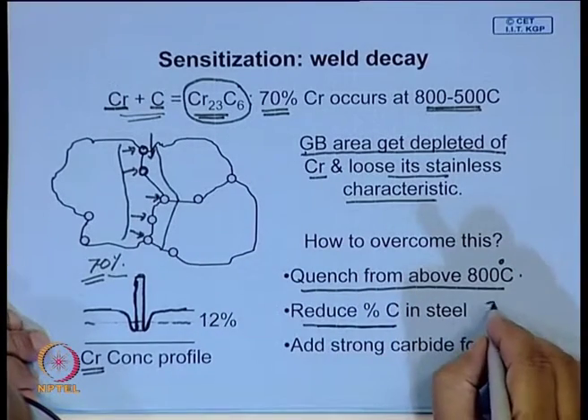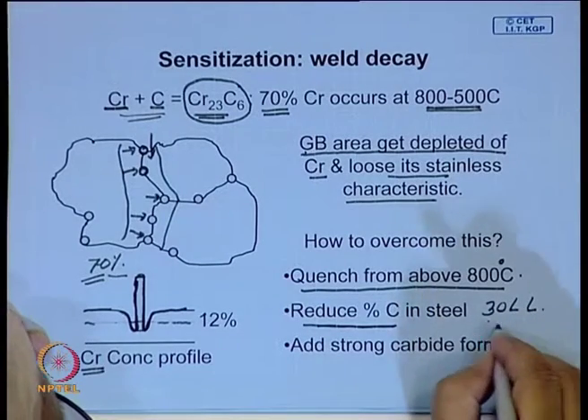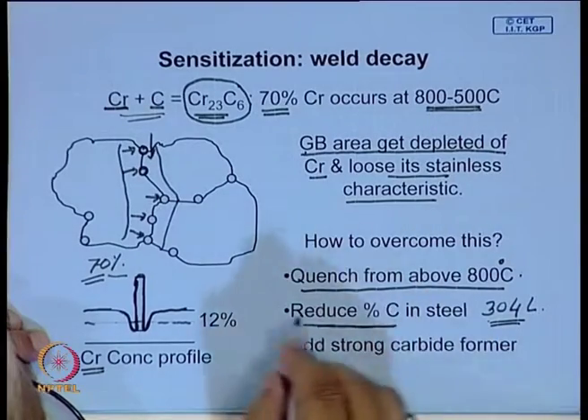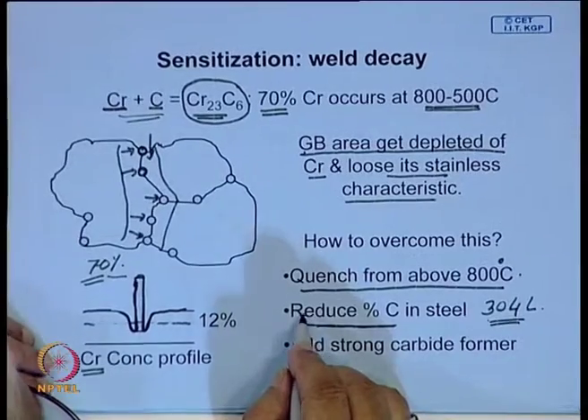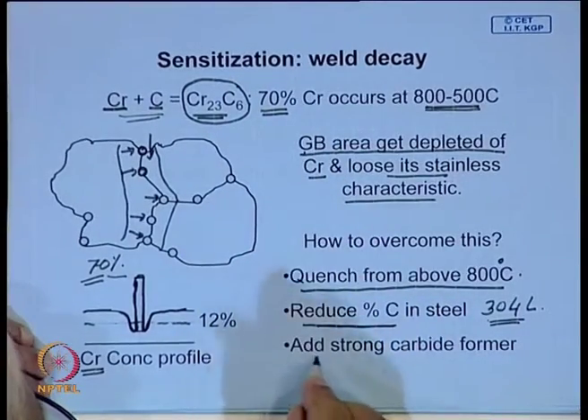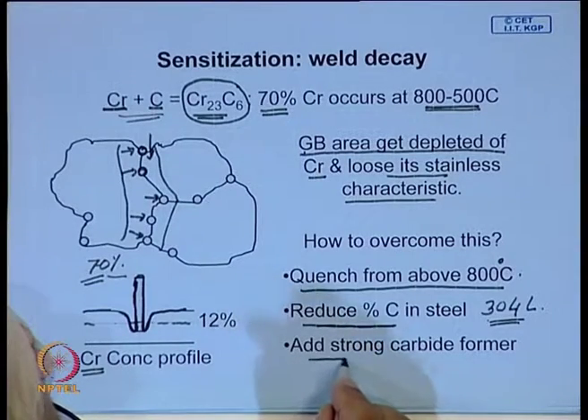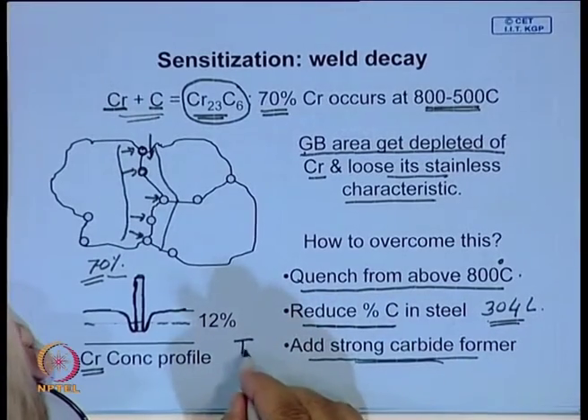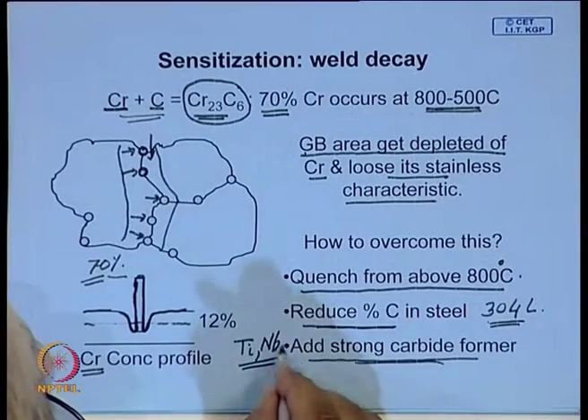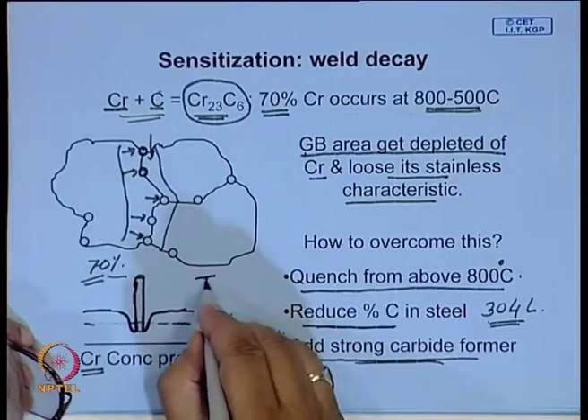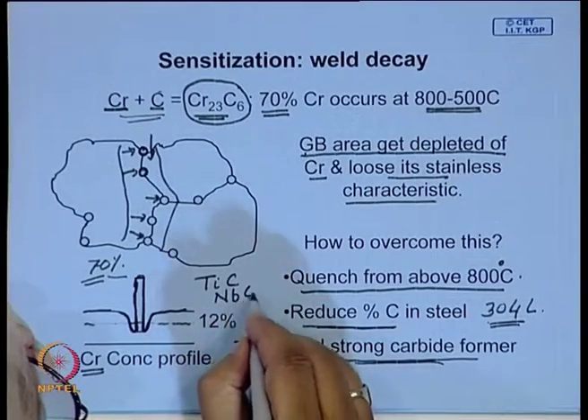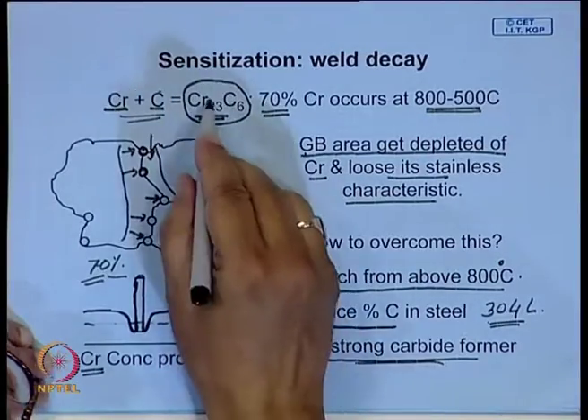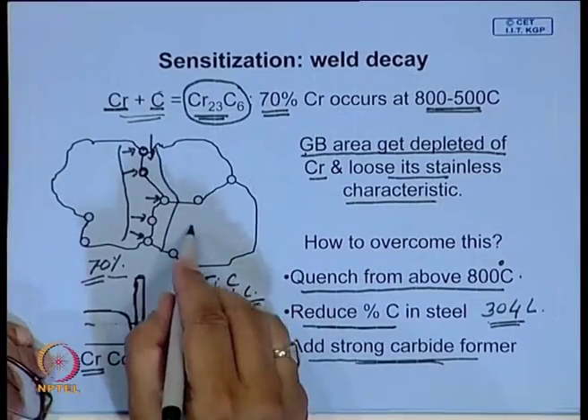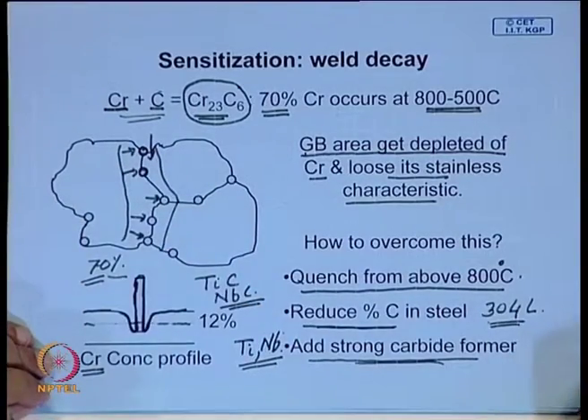So, there are certain grades like 304L with a very low carbon. In that case, it will not be susceptible to this sensitization problem. Another, more common way of avoiding it is to add a strong carbide former like titanium or niobium. This reacts with carbon and forms titanium carbide or niobium carbide, which have a stronger affinity for carbon than chromium. Therefore, chromium does not get enough carbon to react with, and is forced to remain in solid solution. These are the very common ways of avoiding the sensitization problem in steel.